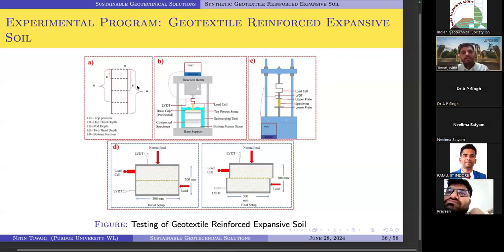So we worked it out and figured it out. If we place it at different depths, for example, 1/3, 2/3, half, and bottom, how will it affect the swelling behavior? As obvious, if you place it at the bottom, it will not work out really well, but the drainage will improve for sure. So we placed it at the different places, and then we conducted two tests. Back in those days when I was doing this, we didn't have a triaxial, so we could not do the triaxial, but we did the UCS test and upward swelling pressure test.